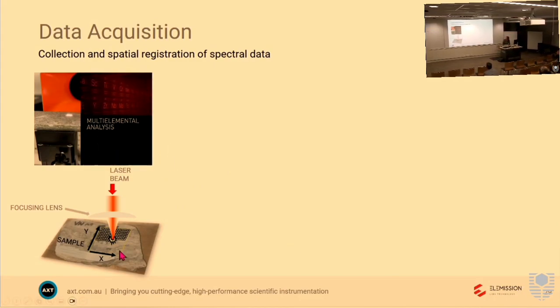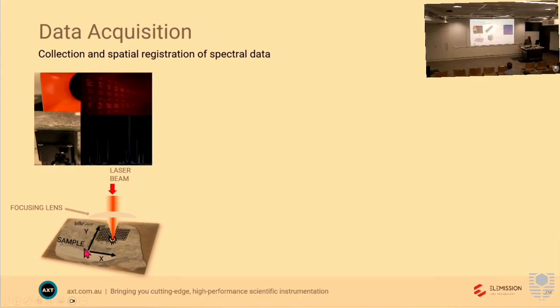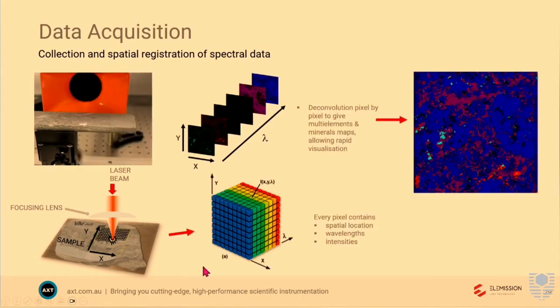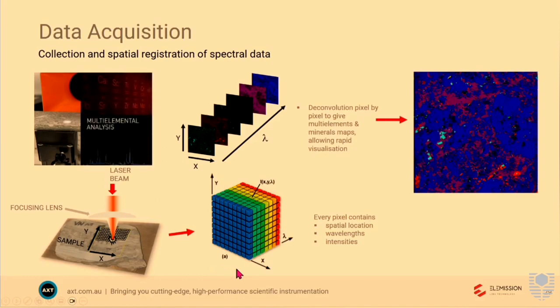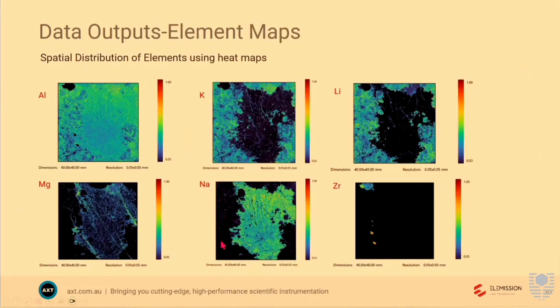Like SEM technology, it rasters in a square, a field, a rectangle. So for every pixel, you've got the spatial coordinates, the wavelengths and the intensities. Software deconvolutes it element by element, and you end up with a multi-element image, a bit similar to SEM technology. And you get these heat maps. Where it's red, it's the most intense. Where it's black or dark, you have absolutely nothing. So it's an instant way of telling you the element association with each other without doing any mineralogy.